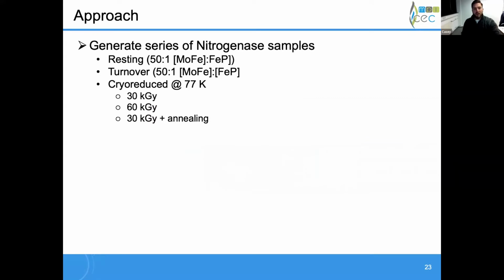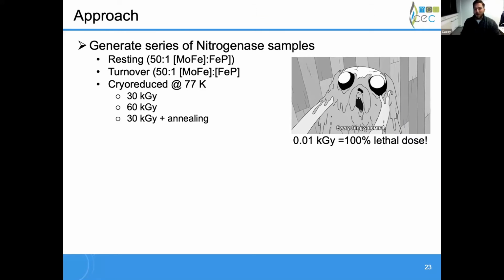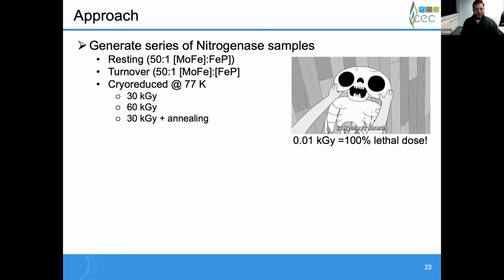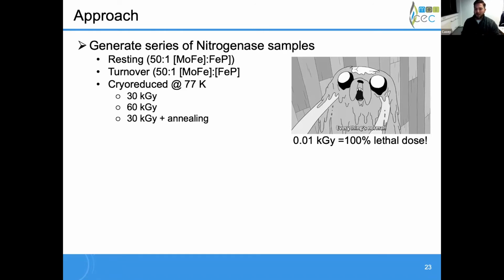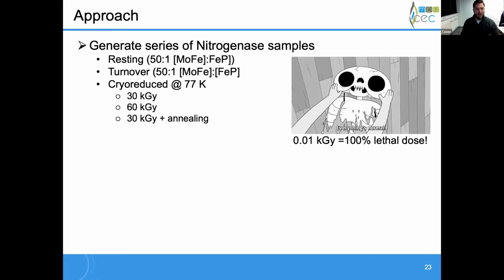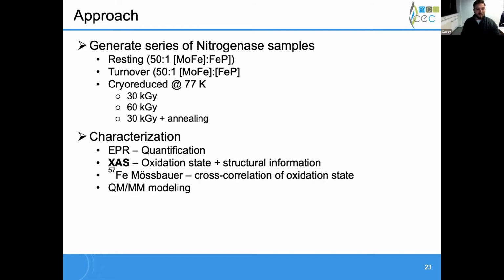And so we generated a series of samples, both resting, turnover, and several different conditions of cryoreduction, as well as annealed cryoreduced samples. And then, I forgot to mention, 30 kilogray is an amazingly large amount of radiation. It is very difficult to reduce this protein. For example, 0.01 kilogray is a 100% lethal dose in humans. So just a perspective that these do not damage very easily under irradiation.